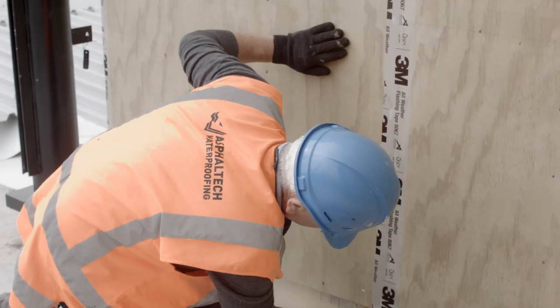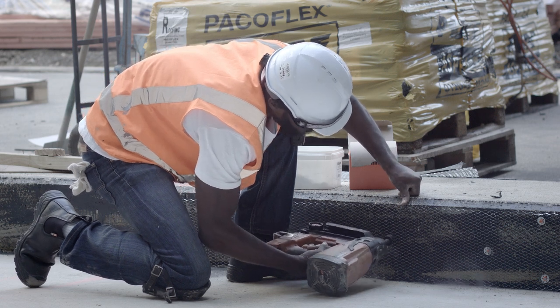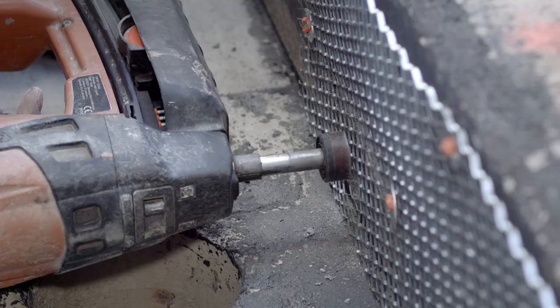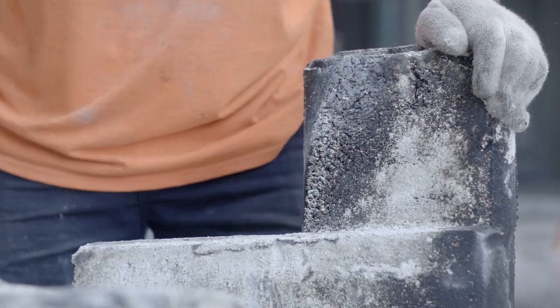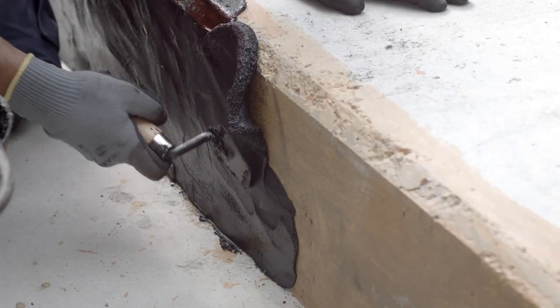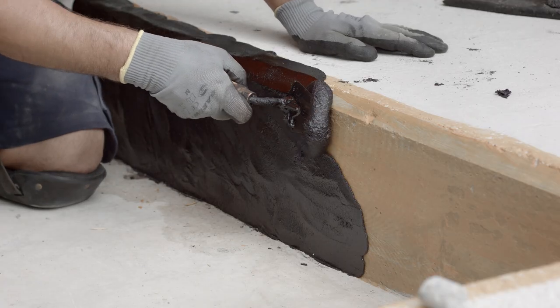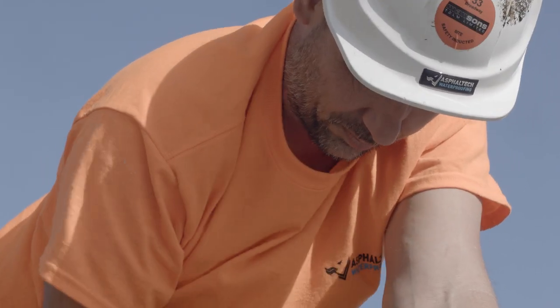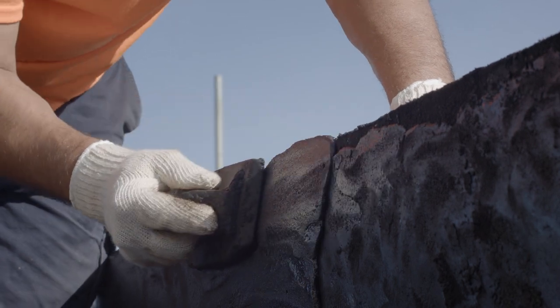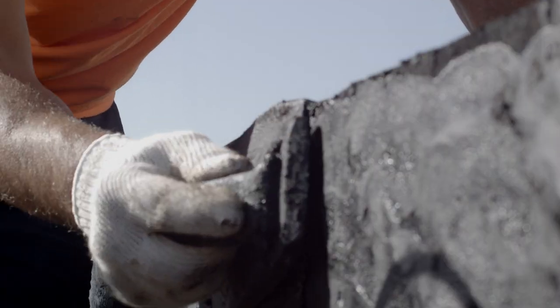The vertical surface. A primer coat should be applied to the vertical surface to allow the Mastic Asphalt to bond. Expanded metal lathe should be incorporated to surfaces if the height is greater than 300 millimetres. The Mastic product is unpacked and heated in the Mastic Asphalt mixer where it can be easily distributed to the working areas. The first layer is then applied by trowel or wooden float. The second layer is then applied creating a smooth monolithic finish. The complete thickness should total 13 millimetres, plus or minus three.